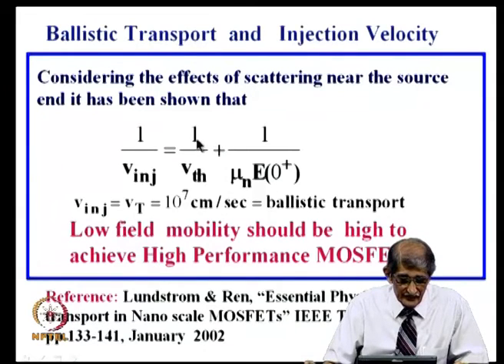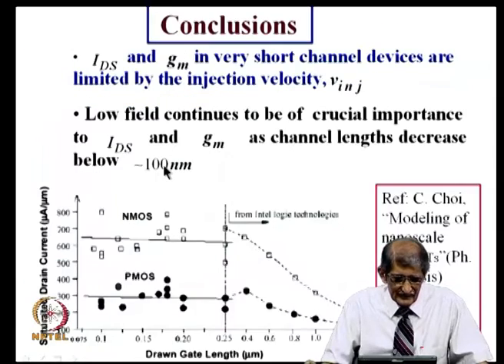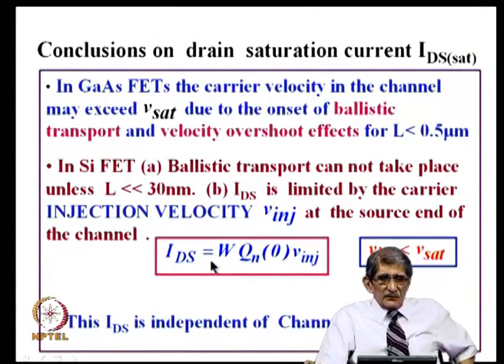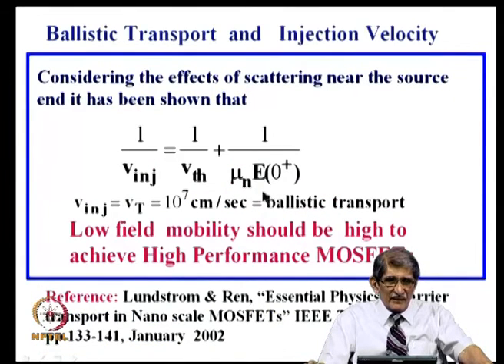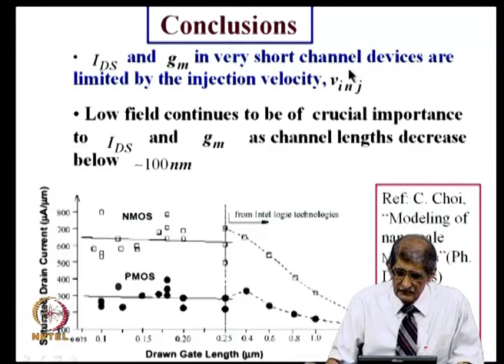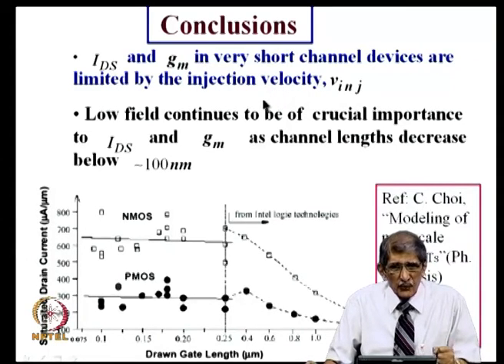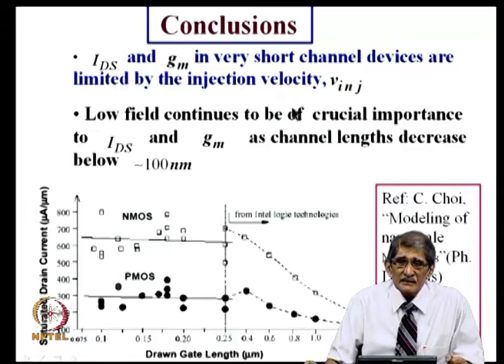Considering both these effects together, what you would say is that you can still write the drain current is equal to WQ into injection velocity. Injection velocity is the combined effect of these two terms. If I have high mobility in the channel, you may get thermal velocity itself very close to saturation velocity, but it will always be less than that. But if the mobility is low, then it will be far below the thermal velocity, saturation velocity. So, you can see that this particular term, drain current that you get, saturation drain current, will be in the very short channel devices limited by the injection velocity, which is controlled by both saturation velocity or thermal velocity and the mobility.